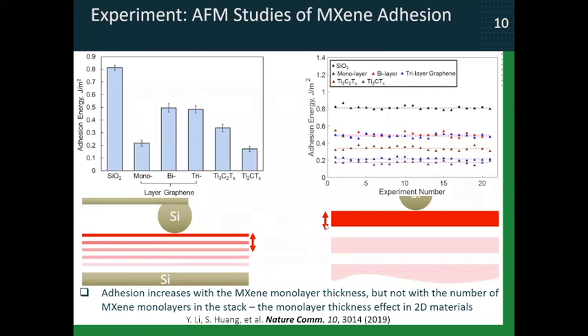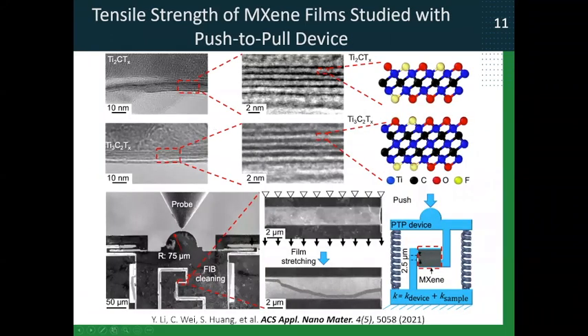We also studied properties of multi-layer MXene films, which we fabricate using interfacial film deposition. And the way we studied mechanical properties of these films was by using a device called a push-to-pull device in SEM with a picoindenter. So here is the picoindenter, which we use as a source of force. It basically pushes with a given force on this part of the push-to-pull device, which is shown here, and its schematic is presented here. The essence of this device is that when you push on this part, it stretches the material which is deposited here. The design of this device is such that by pushing on one side, you stretch the material which is deposited over this gap.